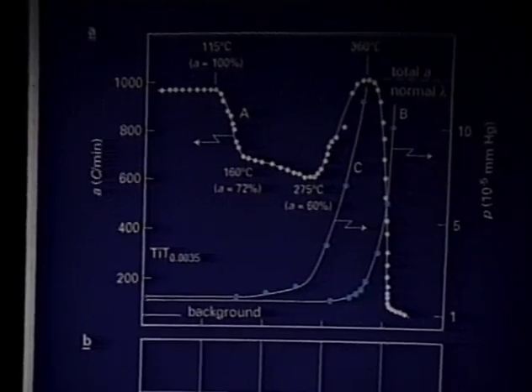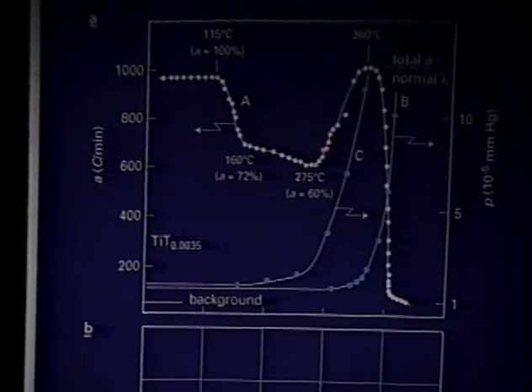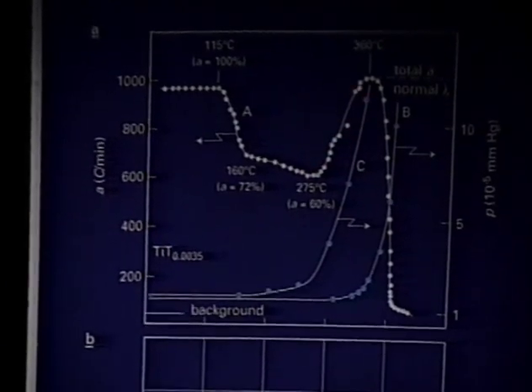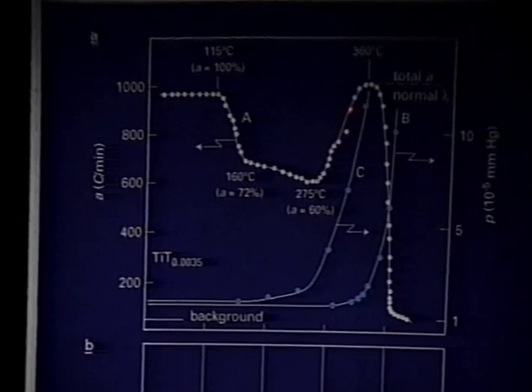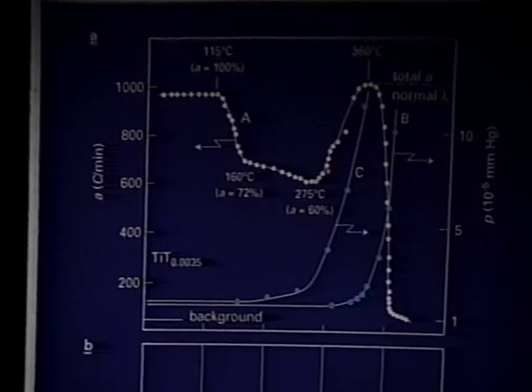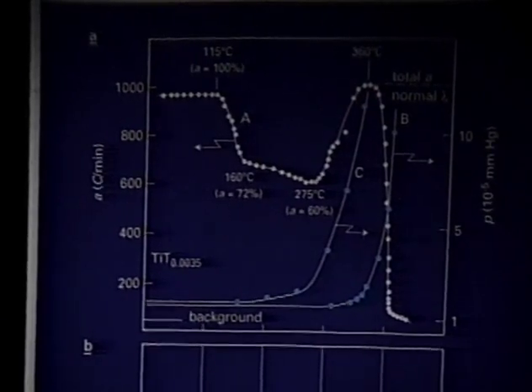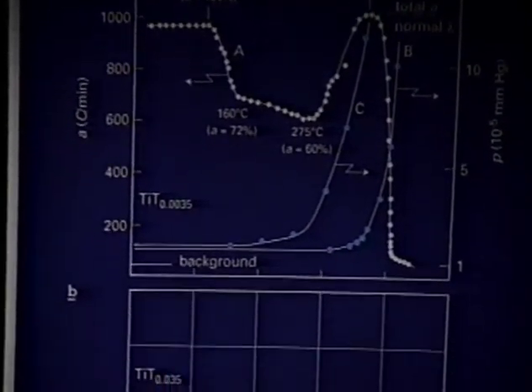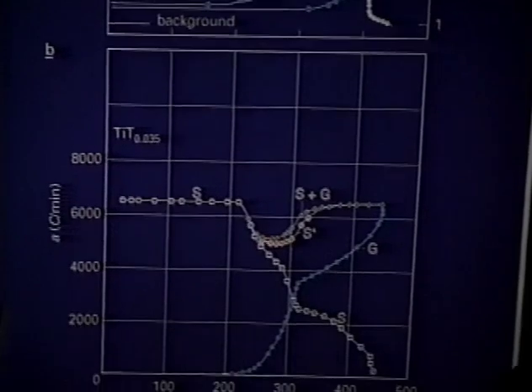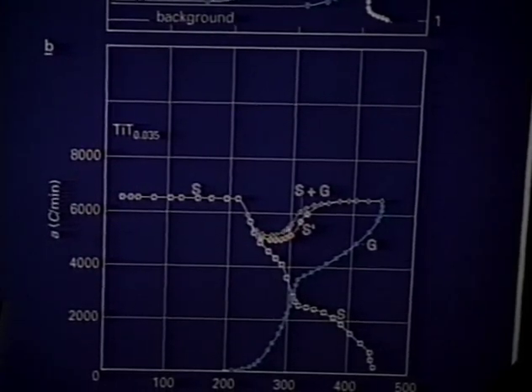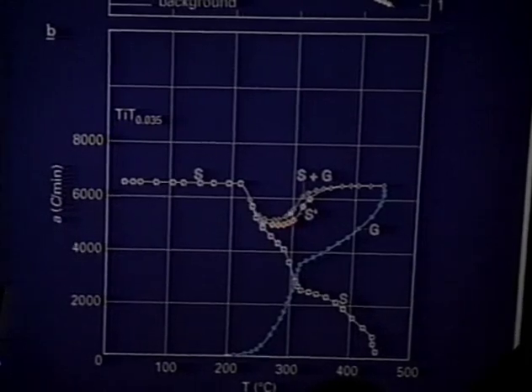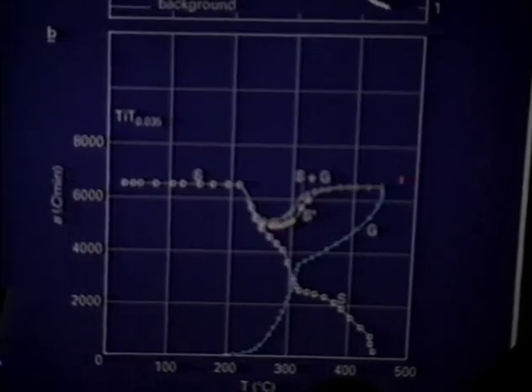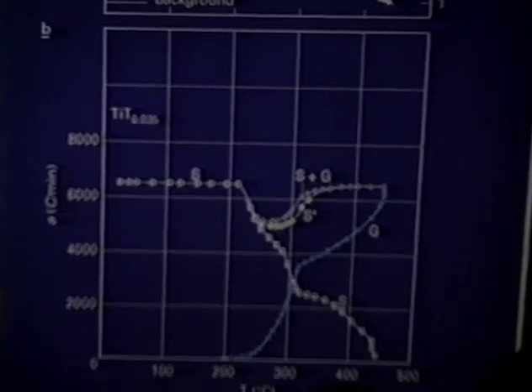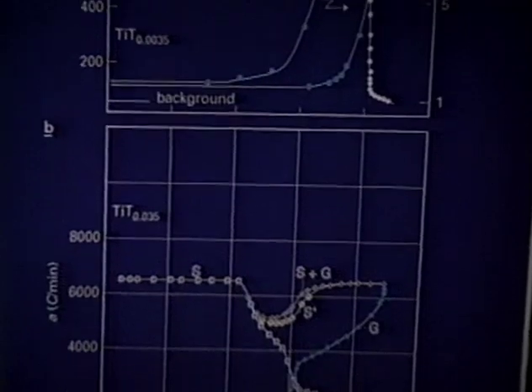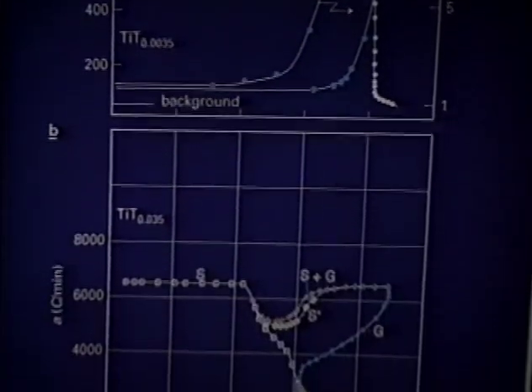With the first experiment, the tritium atoms which retain normal radioactivity remain in the preparation. They cannot leave it on account of surface contamination. And with the second experiment, the tritium atoms which release their bonds to the titanium lattice leave the preparation, but the total radioactivity has the same course as with the first experiment. The only difference is that here the tritium atoms remain in the preparation, and with this experiment they leave the preparation.